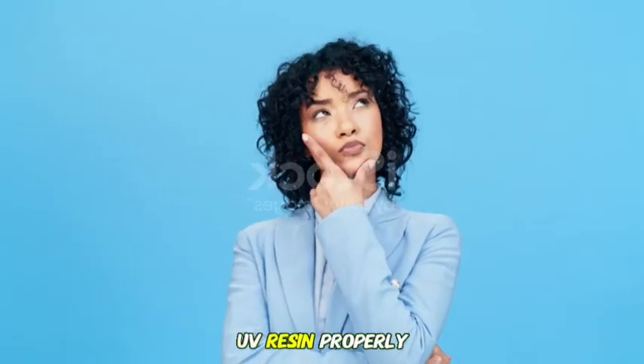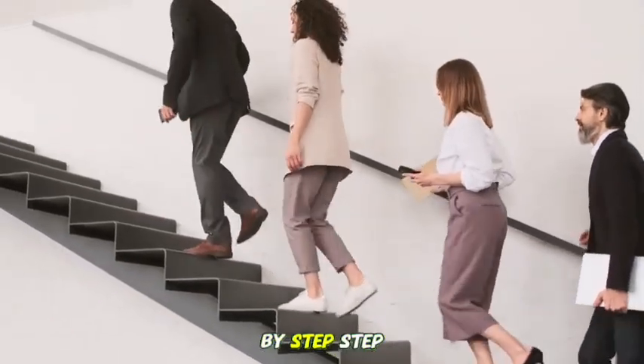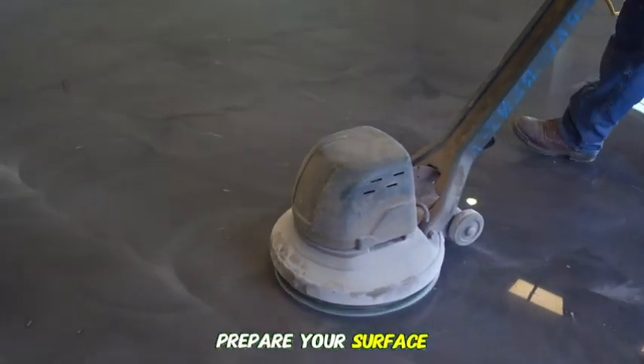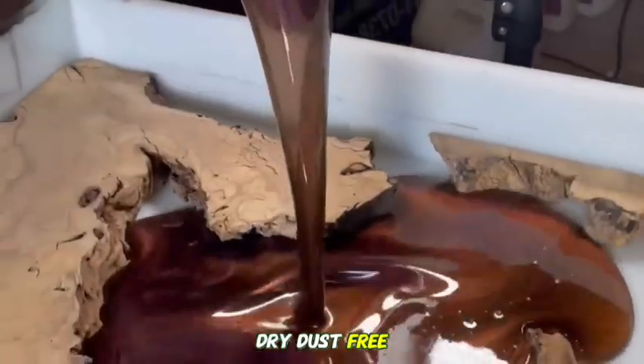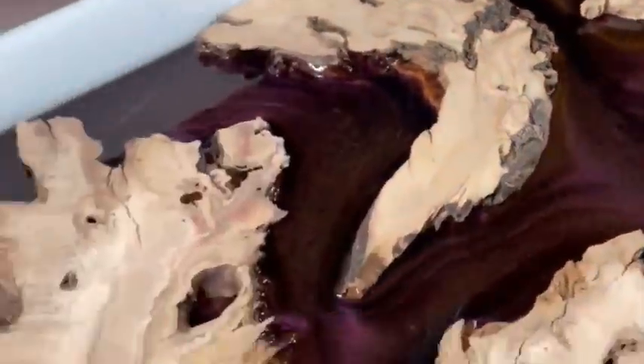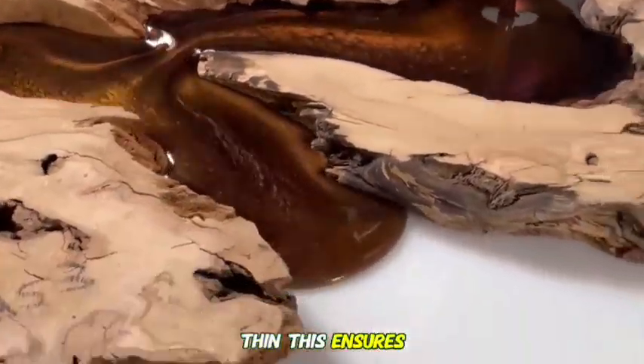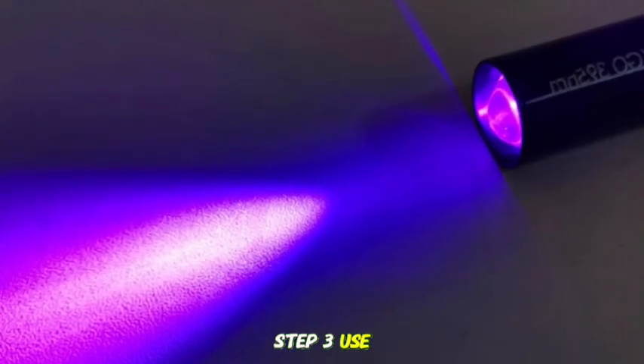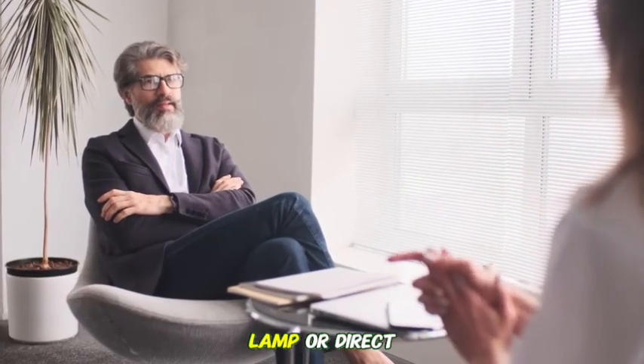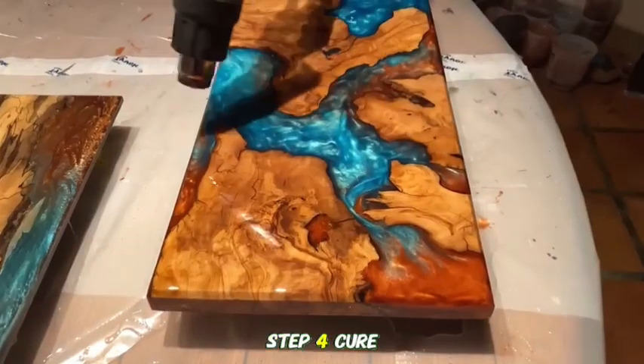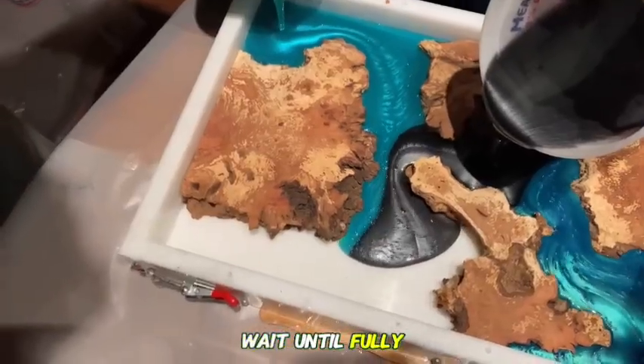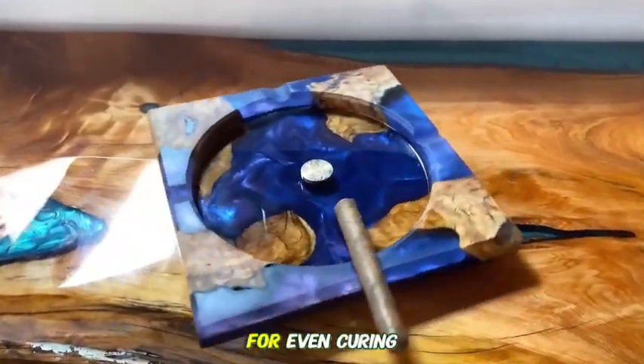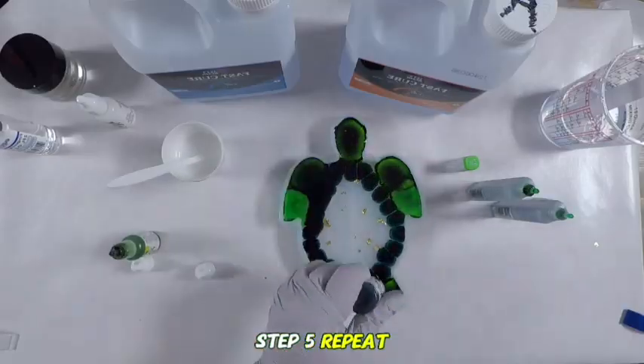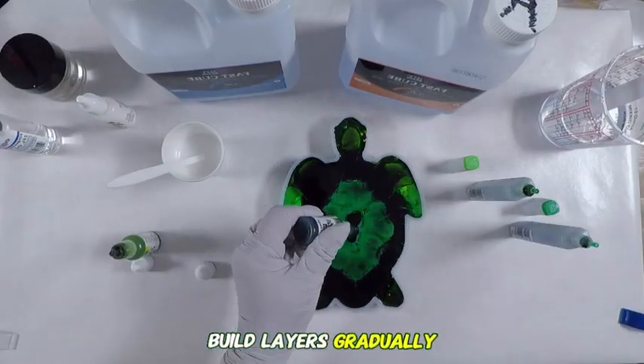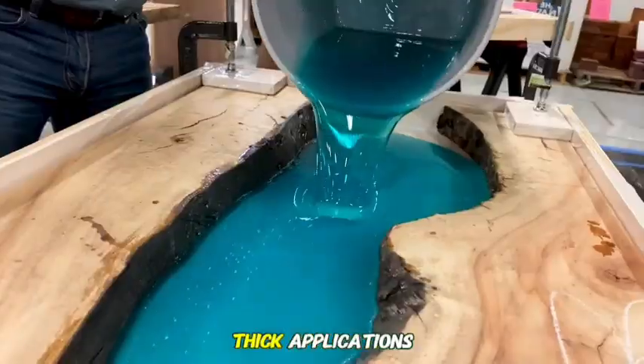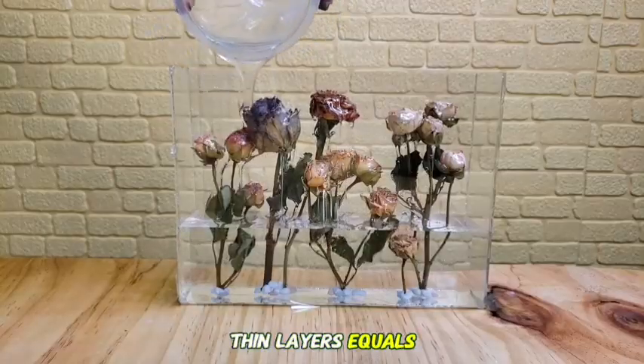How to use UV resin properly. Let's go step by step. Step 1. Prepare your surface. Clean, dry, dust-free. Step 2. Apply thin layers. Always keep layers thin. This ensures proper curing. Step 3. Use UV light. Place under UV lamp or direct sunlight. Step 4. Cure properly. Wait until fully hardened. Rotate if needed for even curing. Step 5. Repeat if needed. Build layers gradually. Pro tip: do not rush thick applications. Thin layers equals better results.